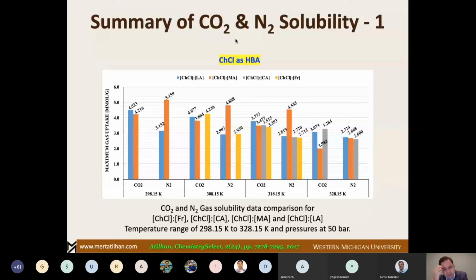Yeah, we gathered the data, but this time we got better performances. At around 50 bar, we increased the pressure from 30 to 50 bar to stretch the limit of the equipment. So obviously, we are here talking about 4.5, 4.8 CO2 millimole per gram of deep eutectic solvent.